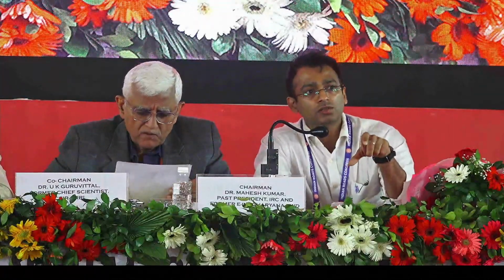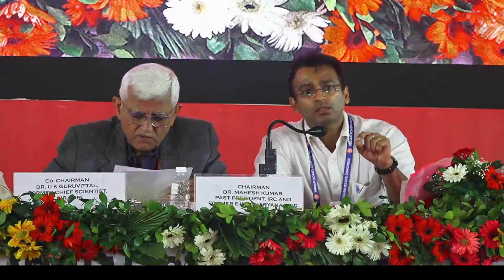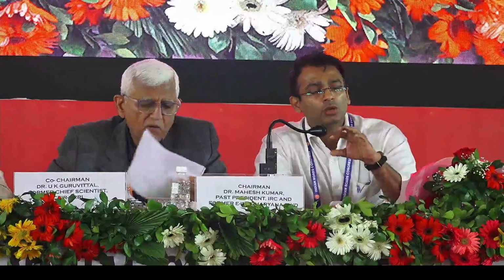In order to simulate all these conditions, because these conditions will finally affect the parameter which we are trying to propose using the dynamic creep test, this is the reason we varied the compaction level: to understand how the change in volumetrics will change the performance over a period of time. And we could have a plot of the performance model of these typical mixes which we use in Indian conditions.